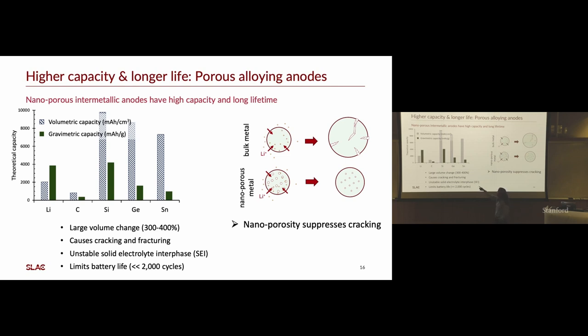Lithium is actually what people are mainly trying to do, lithium metal. Silicon is a great host for lithium. It has a very large volumetric capacity. But there are many problems with silicon. And actually, those problems are the same with germanium and tin. This work is on tin. But we think that a lot of the results from this work could also be mapped onto solutions for silicon anodes.